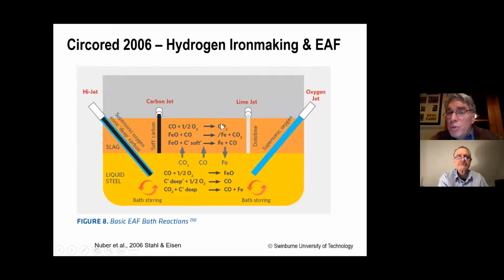And they also had to put carbon in to make sure they got good stirring in the bath, because the carbon does more than just take away the oxygen, carbon is used all through the steelmaking process. And so they had to adapt the electric arc furnace steelmaking process for this kind of iron, and it was not trivial. It was actually fairly challenging. And if we go to a large scale, these problems will get even worse.